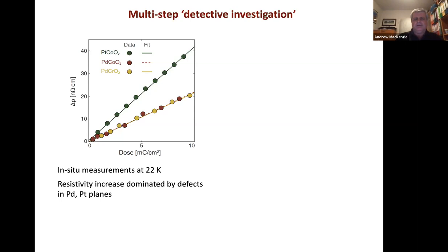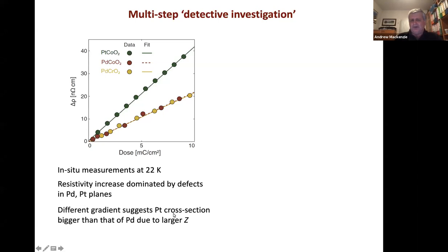So once all of that process had gone through, this is the kind of thing they're able to see. Gratifyingly, the resistivity grows with the dose. And it grows with the dose at a different rate in platinum cobaltate than it does in either palladium cobaltate or palladium chromate. So rather clearly, the increase is dominated by defects in the palladium or platinum planes. And the reason the gradients are different suggests that the platinum cross-section would be bigger than that of palladium because it has a larger atomic number. Now, we all remember that from the Rutherford experiment and thinking about alpha particles and the Rutherford cross-section.